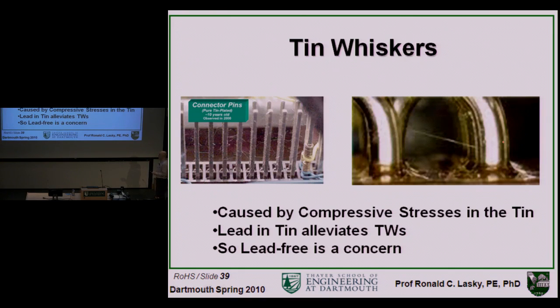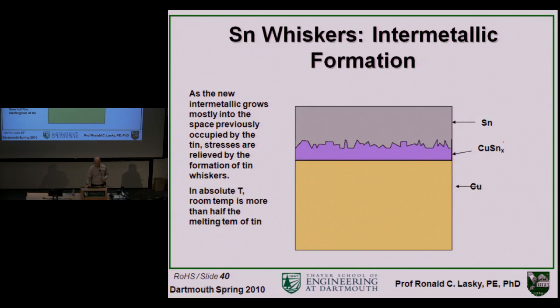The lead in tin, when we were in an era where these coatings would have lead in them, the lead solid solution strengthens the tin. And even if there is a compressive stress, from a layman's perspective, the tin whisker doesn't start to form because of the strength of the matrix due to the solid solution strengthening of the tin. So in lead-free, this is quite a concern.